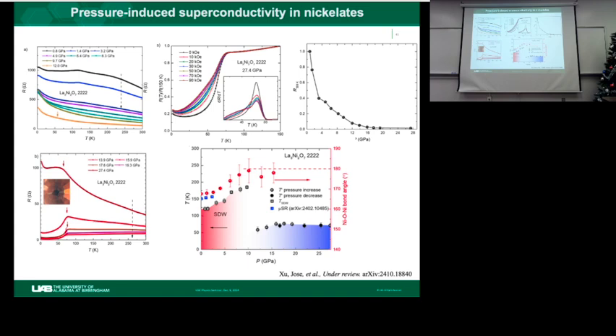Yeah, we normally use platinum. Platinum is not a superconductor under very high pressure. People have done that. And so the material of the probes is carefully chosen. And as I showed earlier, you could fabricate the probes on the diamond cell on the tip, and very often we use tungsten. And tungsten doesn't superconduct under very high pressure either.